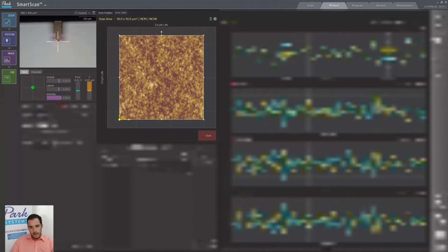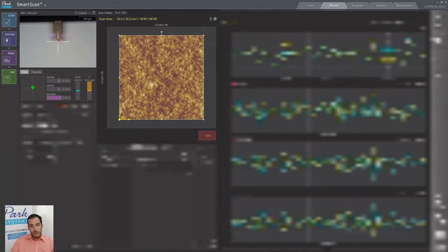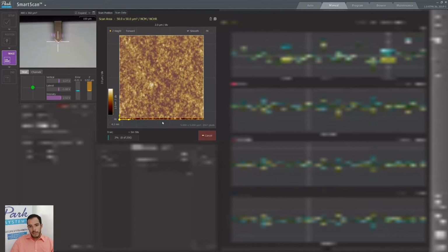Just to make this comparable with the previous image we have, we're going to use the same settings. So 13.9 nanometers as a set point and 0.7 for the Z-servo gain for both of them. And when we are ready, we just have to go back to the scan button and click on it and we'll start scanning. And right now we just have to wait a couple of seconds to start seeing our created features,